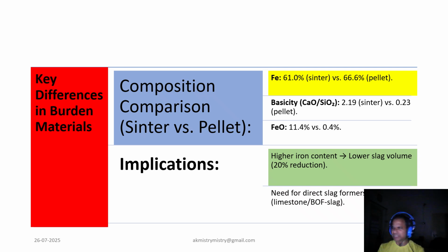Now, it is very important to see the challenges. Unless we differentiate the composition of the sinter and pellet, we could not trace the challenge. Hence, it is essential to share the compositional variance of the burden components. One of the most striking differences between sinter and pellet, as shown in the slide, lies in the composition. As I have mentioned, pellet offered higher Fe content, around 66% and more, compared to 61% in sinter. Of course, it's higher compared to the usual context of sinter, and a much lower Al2O3.